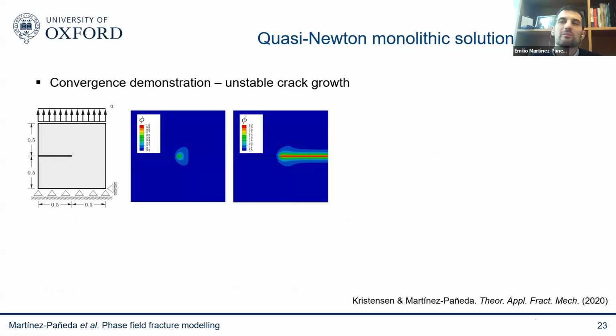So this is a classic benchmark example. This is a classic benchmark in the phase field community. You have a plate, square plate, with a crack subjected to uniaxial tension. The material is linear elastic, so mode 1 fracture, you apply a load, the crack is going to grow in an unstable fashion. You pull, and the crack will go immediately in one step across the entire plate because it's a linear elastic material. It's mode 1 fracture, it will just grow unstable.